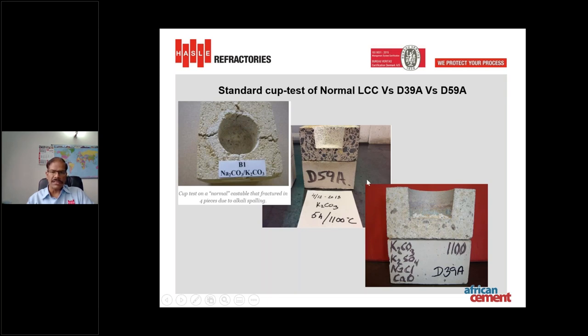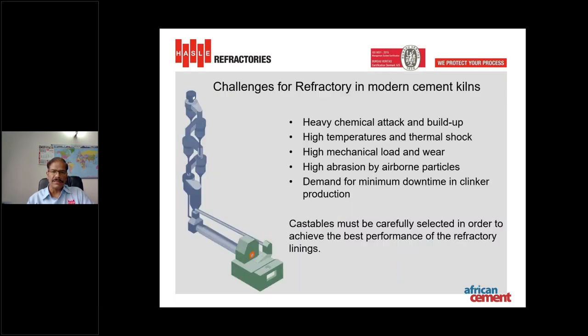Here we do these tests with our products like D59A and D39A. We make a cup of our castable, put alkali sulfate and alkali chlorides in it, heat it for 5 hours at 1100 degrees centigrade, and see what the penetration level is and what the reaction with the surface of the refractory is. In our case, this penetration and reaction is very minimal. On the other hand, you can see what happens if your refractory is not suitable for these alkali sulfates and chlorides. It hampers the performance of the refractories.